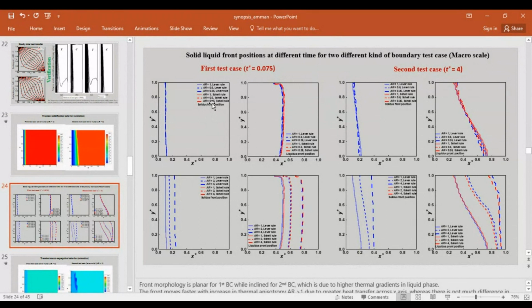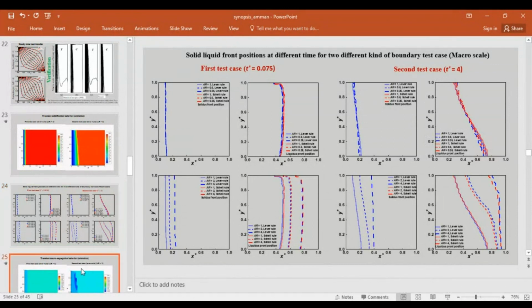So here we can see that when we change the anisotropy ratio, this is the solidus front position and this is the liquidus front position. The liquidus front position changes when we change the anisotropy ratio. We increase the anisotropy ratio, AR equal to 1, 2, 3. For both the Lever rule and Scheil model, we can see the front moves faster. Similarly, for the second test case, when we increase the anisotropy ratio, the front moves faster, right? So that has been seen.